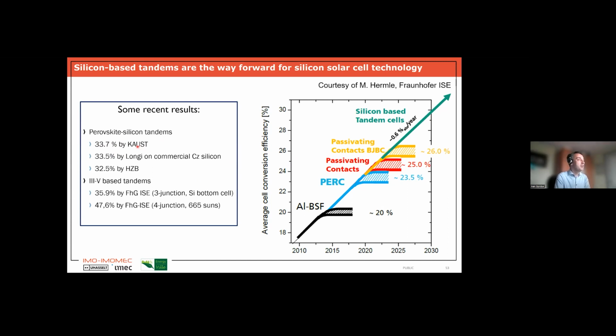So this was obtained by researchers at KAUST in Saudi Arabia. A Chinese company, Longi, on commercial CZ silicon wafers has also reached a very high efficiency, 33.5%. And before the world record of KAUST, HZB in Berlin also had a world record of 32.5%. So it shows you many groups are getting very high efficiencies, and almost monthly we see higher efficiencies. Now, in principle, we can also use other materials than perovskite as the top cell. For instance, we could go to III-V based tandems, where also very high efficiencies can be reached. But of course, III-V materials are typically quite expensive.